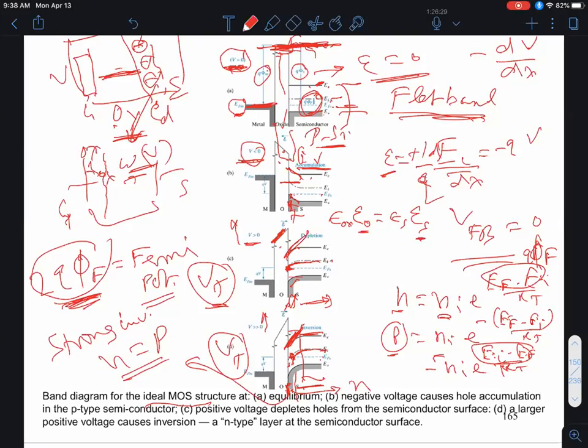These are given by the band edges. These are the dielectric constants. Now, just for calibration, the relative dielectric constant of SiO2 is around 4, and that of silicon is around 12, approximately. So therefore, these slopes will have a ratio of 1 to 3. So these are known as electric displacements. Now, if you have a sheet charge right at the interface, that has to be added to that. So if I have an interface charge, Q interface, that enters into this equation over here.